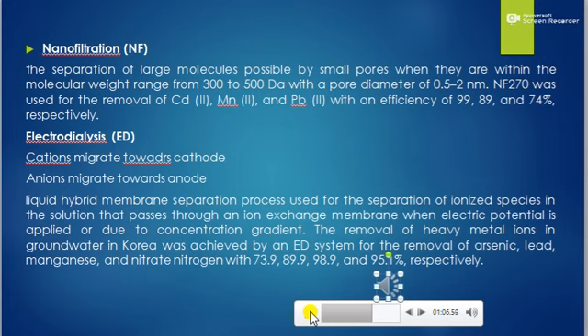Liquid hybrid membrane separation process used for the separation of ionized species in the solution that passes through an ion exchange membrane when electrical potential is applied or due to concentration gradient. The removal of heavy metal ions in groundwater in Korea was achieved by electrodialysis system for the removal of arsenic, lead and nitrate, nitrogen and efficiency of approximately 73.9 to 95.1% respectively.